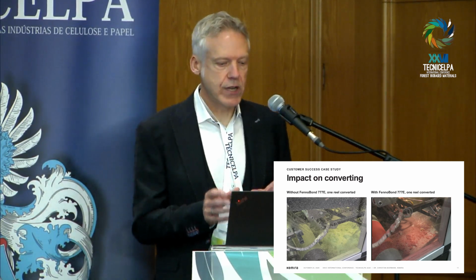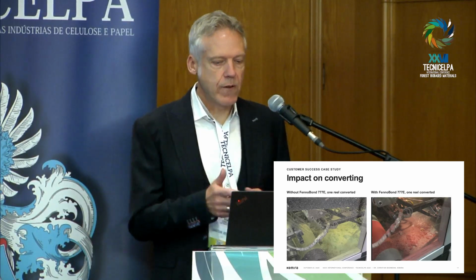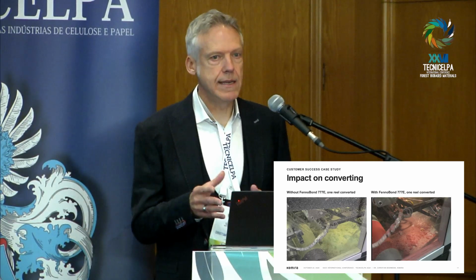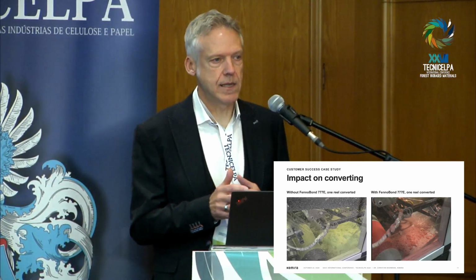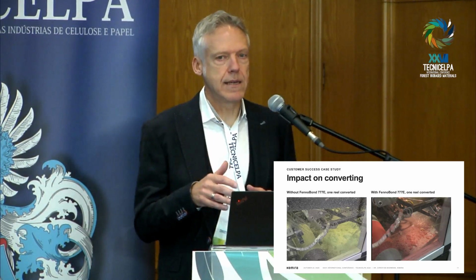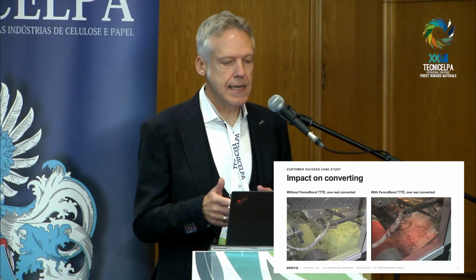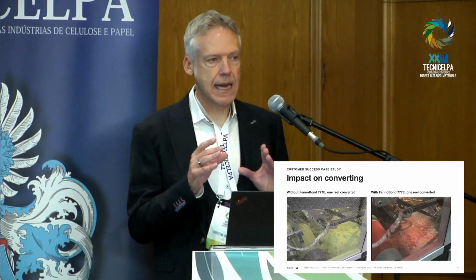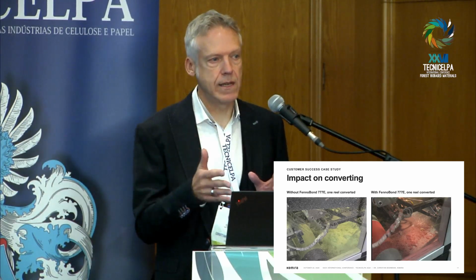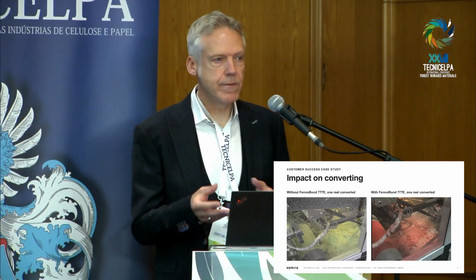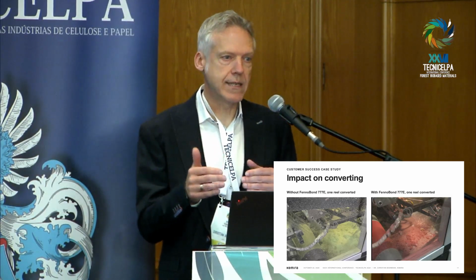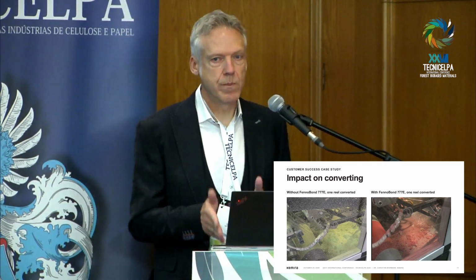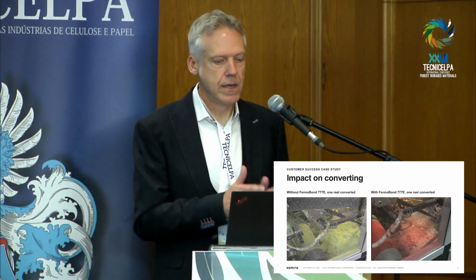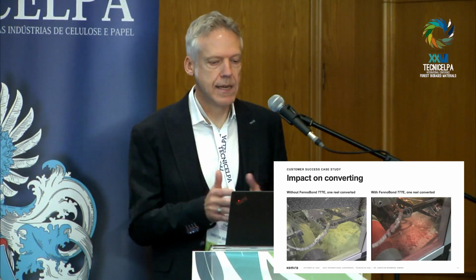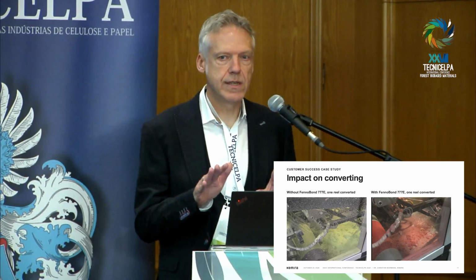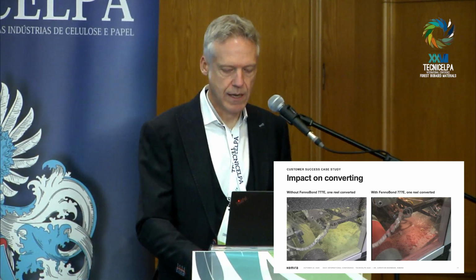And maybe one thing which I didn't mention so far, what we observed was, even though our product is cationic, we see a very small impact on the charge of the system. So zeta stays more or less stable, and colloidal load also stays stable. And as said, this paper machine produces some highly colored grades, and then they need to use a lot of fixative to avoid bleeding of the colors. And we were a little bit afraid that we get too close to the isoelectrical point. But this didn't happen. So the machine stayed anionic all the time, no runnability issues like foam or otherwise. So that's really nice, that we have no limitations, even if the machine is close to the isoelectrical point. So that was really nice.